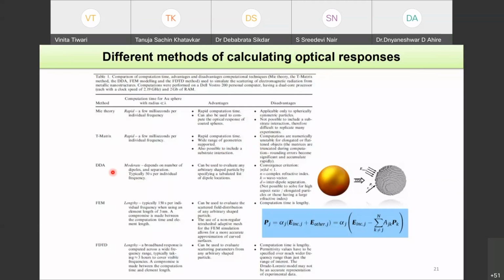Then there is the discrete dipole approximation, which is shown here. You can approximate any shape nanoparticle as a 3D array of dipoles. But then again, there is a convergence criterion, which is that the modulus of nkd should be less than 1, where n is the complex refractive index, and k and d are the wave vector and the interdipole separation.